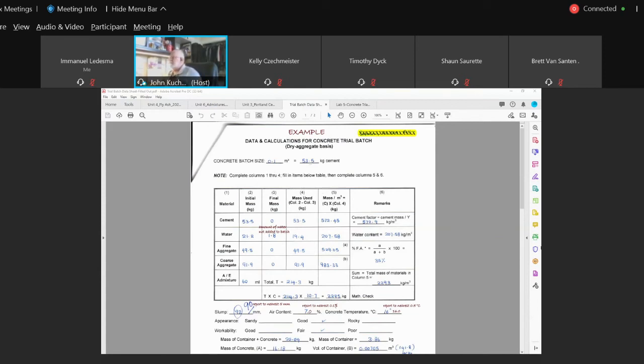Not workability. Now, that's an argument. A lot of people say, no, it is workability. No, it's not. If you did a slump on concrete mix A, and you did a slump on concrete mix B, and they were both the same slump, but one you can finish really well and one is impossible to finish, how could that be workability? They're both the same slump. If you're using the same mix, it's an indication maybe of workability because the slump on the same mix.